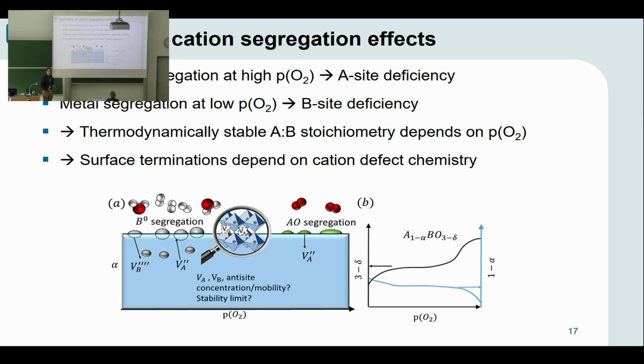So to sum up, we have found that in higher oxygen partial pressures, strontium and A-site-rich precipitates form on the surface, and this leads to A-site deficiency in the perovskite lattice. In reducing conditions, metal ions, especially iron and other reducible transition metals, precipitate to the surface, and this leads to B-site deficiency. So actually, the thermodynamically stable A to B stoichiometry of the perovskite depends on the oxygen partial pressure, and the surface terminations depend also on the cation defect chemistry of the perovskite.